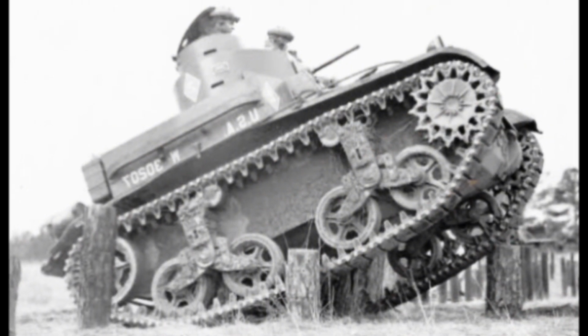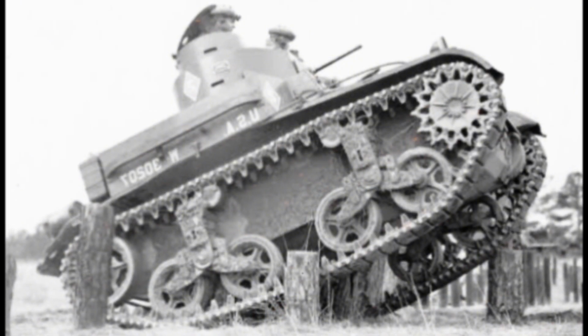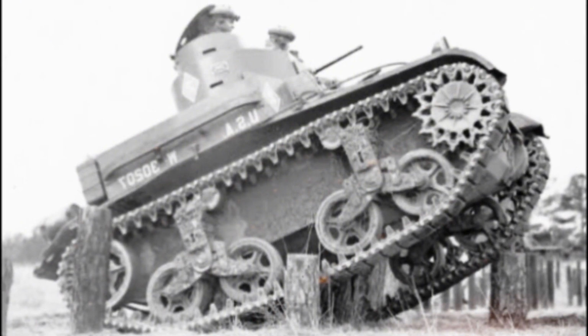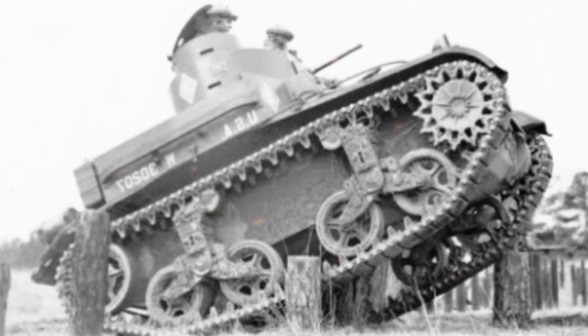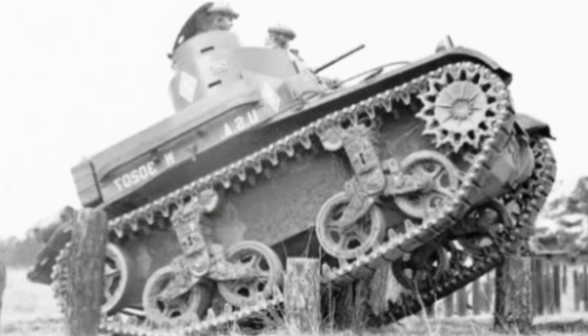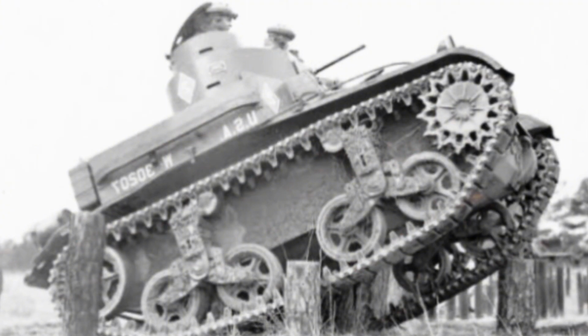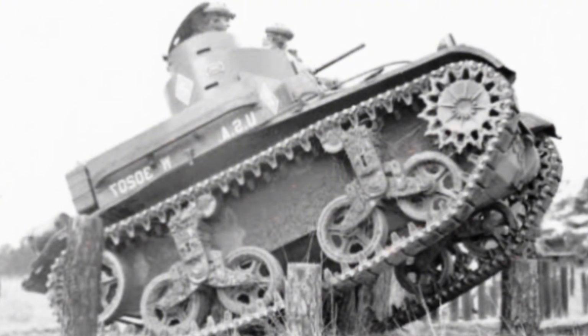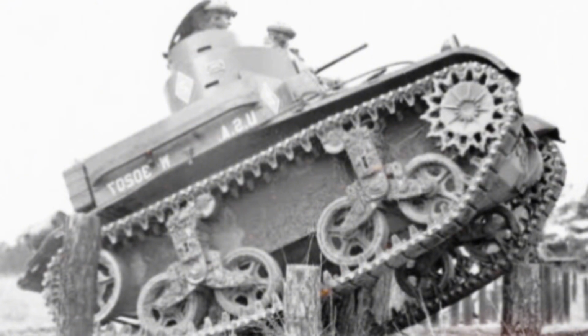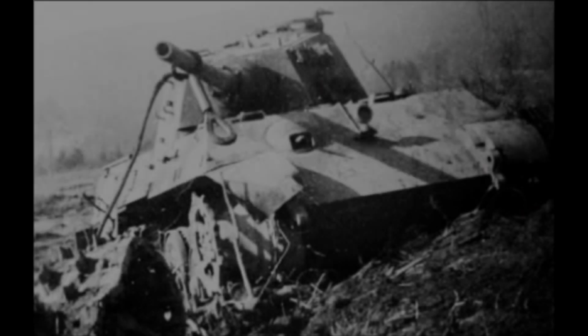The pattern repeated itself. Sicily, Italy, and later Normandy. Tigers were breaking down during combat at rates far exceeding normal mechanical failure rates. German after-action reports described the problem, mentioned transmissions failing during engagement. They attributed it to combat stress, poor maintenance, inadequate spare parts. They never realized the root cause was metallurgical, that the heat treatment process was fundamentally flawed, that every Tiger transmission was in essence a mechanical time bomb.